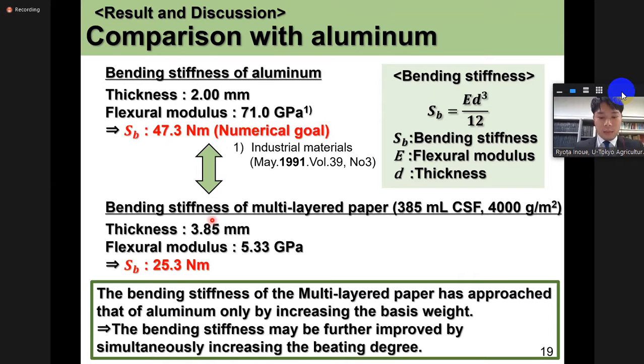On the other hand, the multi-layered paper with the freeness value of 385 milliliters CSF and target base weight of 4,000 gram per square meters has thickness of 3.85 millimeters and flexural modulus of 5.33 gigapascal. So bending stiffness of multi-layered paper is 25.3 Newton meters. The bending stiffness of the multi-layered paper approaches that of aluminum only by increasing the base weight. Therefore, the bending stiffness may be further improved by simultaneously increasing the beating degree.